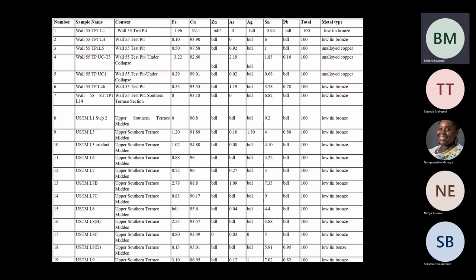So from this, we can actually see that the people who lived at Great Zimbabwe during this period managed to, they were conscious when it comes to the metals that they were mixing. They knew that they could mix a certain amount of tin with copper to create a low tin bronze. And for someone who is interested in archaeometallurgy, in these various cuprous metals, I can say, unfortunately, or fortunately, in other ways, within the 26 samples, we didn't manage to find any evidence of brass. However, we have evidence of unalloyed copper and low tin bronzes. Next slide, please.